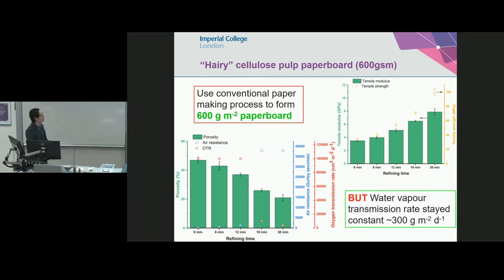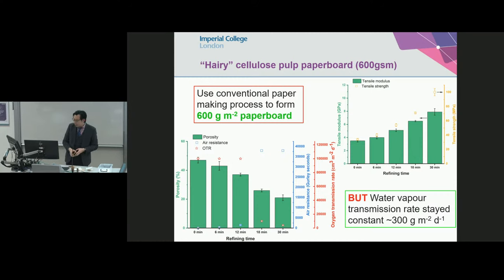And one thing that really surprised us was OTR, oxygen transmission rates. That oxygen transmission rate, that star, actually drops significantly with that refining process. And because of that pore filling effect, you have a lot of pores being filled up, so you have a lot of cellulosic fibers holding each other together, forming a rather rigid material, and you can actually see that the mechanical performance goes up with refining time as well. And lastly, we can also mold them into different structures, like basically molded pulp products, just with lower oxygen transmission rates and better resistance.